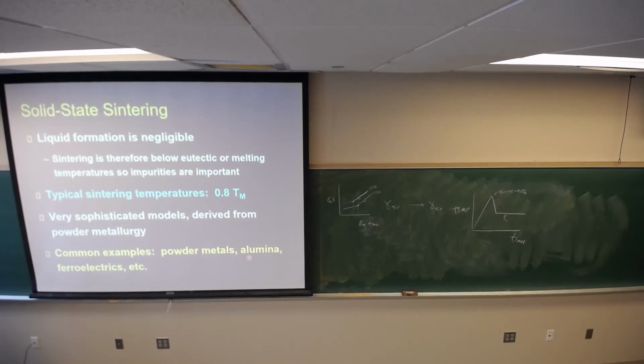Powder metals, by the way, no problem. When you get into ceramics like alumina, small amounts of sodium. Why do I have sodium in alumina? I keep asking this question, see if I get the same response. Yeah, I make the powders with the Bayer process. Typically, you use sodium hydroxide to dissolve aluminum hydrate or hydrated alumina within the bauxite. And when I precipitate out with sulfuric acid, I end up with a little bit of sodium behind. And then I go to great pains to clean that out, but I always have sodium in those systems for the most part.